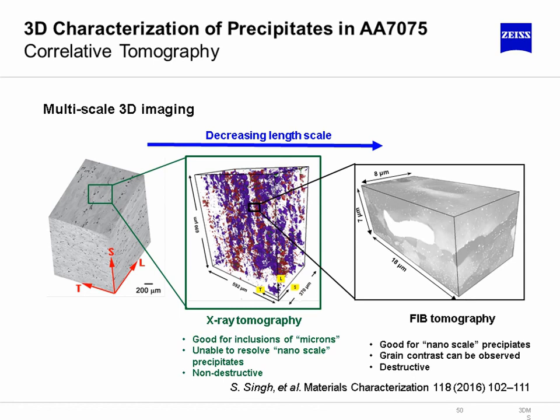Now, to characterize this, we utilize both X-ray tomography as well as FIB-SEM tomography. First, here in purple and red, you see a distribution of these inclusions, these larger scale inclusions. And then finally, on the right-hand side, we really need to zoom into the nanoscale to isolate a single inclusion. You see this bright feature is a silicon-bearing inclusion. We want to understand the distribution of the nanoscale precipitates around that area. Where are they? Are they at the grain boundaries, inside the grains? Are they in the inclusion themselves?